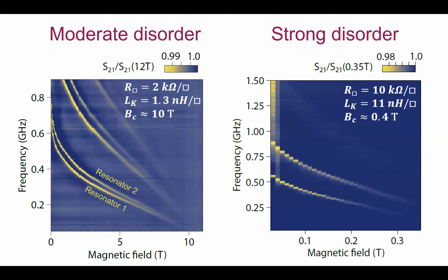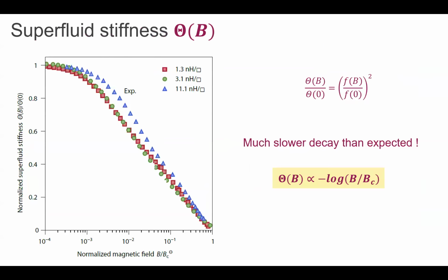so an increase of the inductance. Here we have two resonators. Those are just the harmonics. This is a much more disordered sample. You see the critical field is 0.4. This is where there is this giant magnetoresistance. And now we can take several samples like this and plot the superfluid stiffness, the square of the frequency, as a function of the normalized critical field. And what we obtain is this curve.